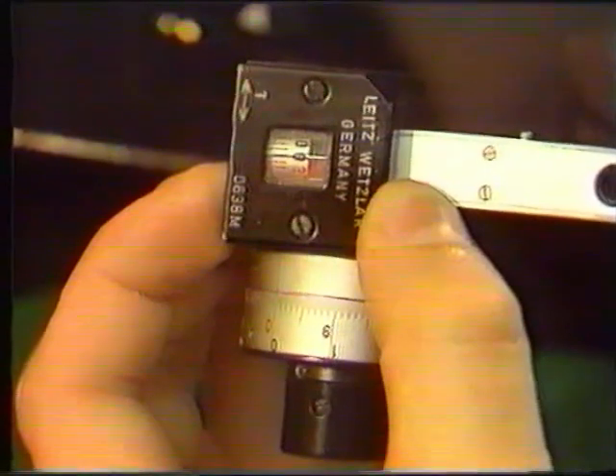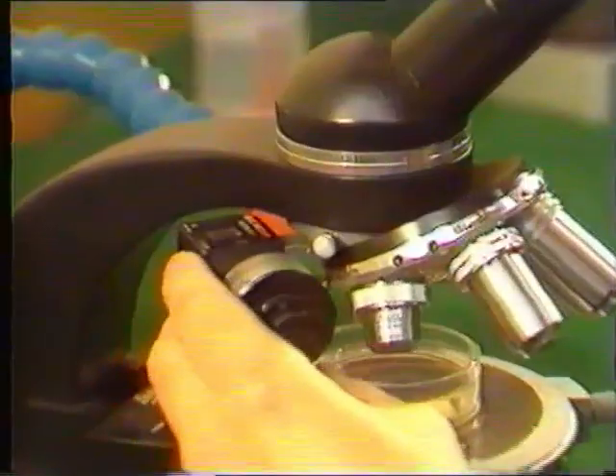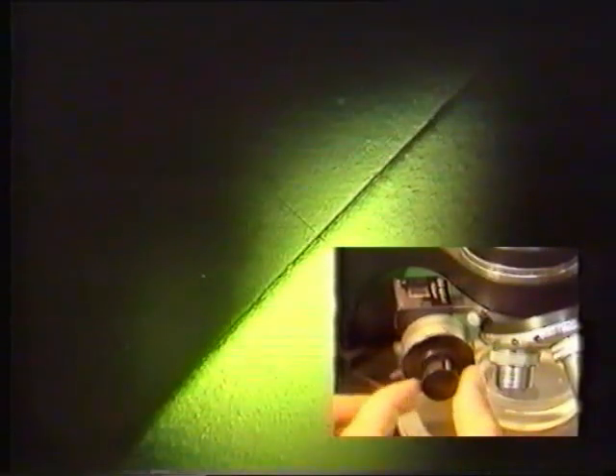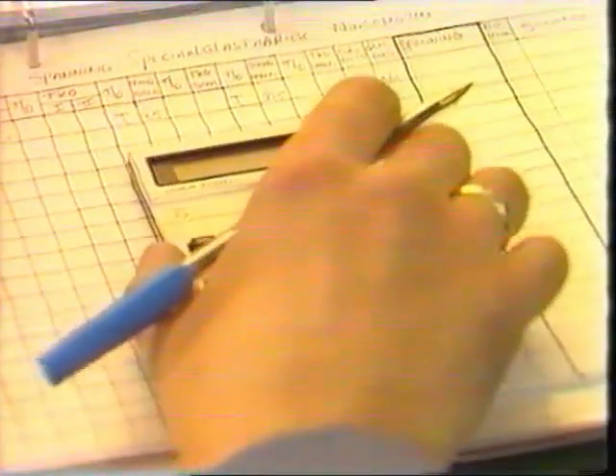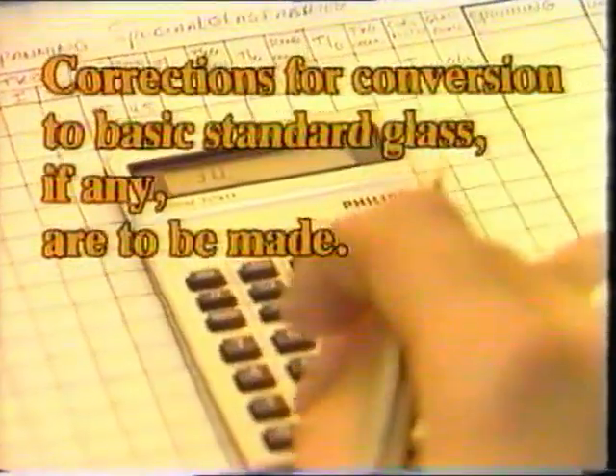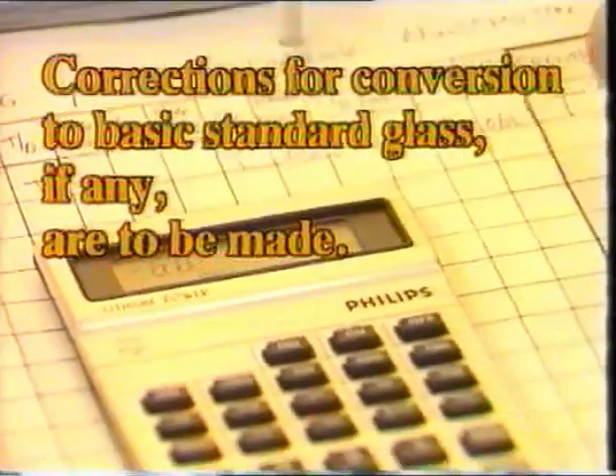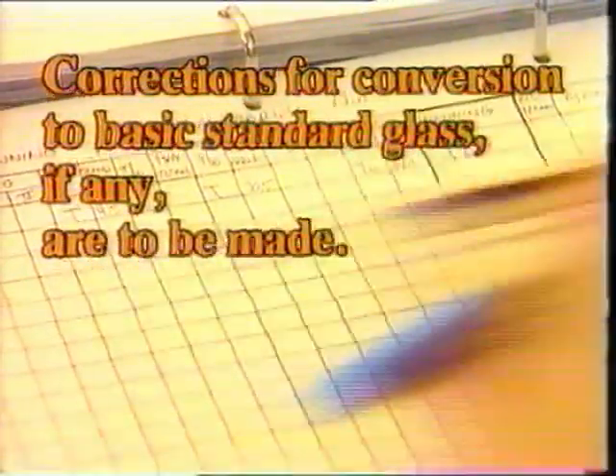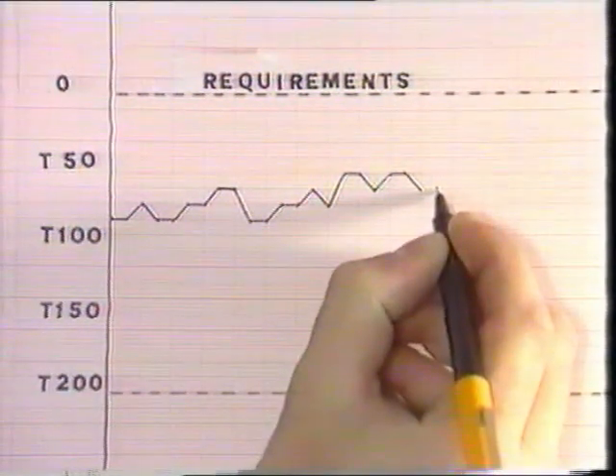The type of stress prevailing in the standard glass is determined. The compensator to be used for measuring the type of stress found in the standard glass is set at 0. The measuring point is obscured by turning the compensator button and partial closure of the diaphragm. This is repeated, but now with the compensator button turned clockwise. The nanometer figure found is divided by the thickness of the strain slab in centimeters. The strain value found is checked against the requirements.